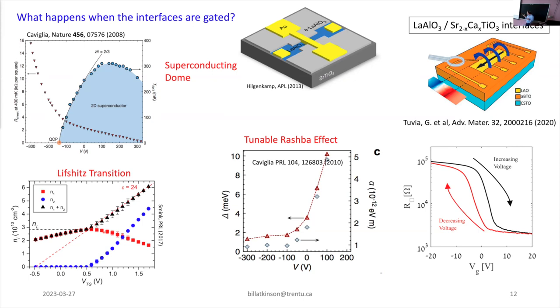After I put this slide together and I was staring at it, I realized that everything on this slide can be plausibly connected to the fact that strontium titanate is almost a ferroelectric, that it's a quantum paraelectric. And I think that's the novelty that really makes these different from a silicon interface or a gallium arsenide interface.